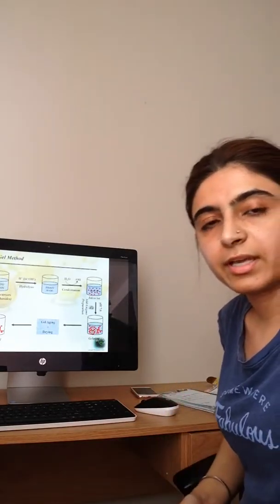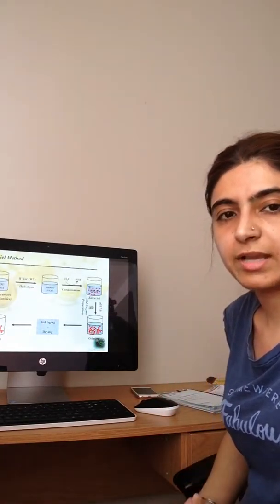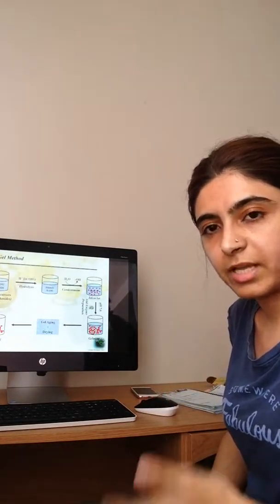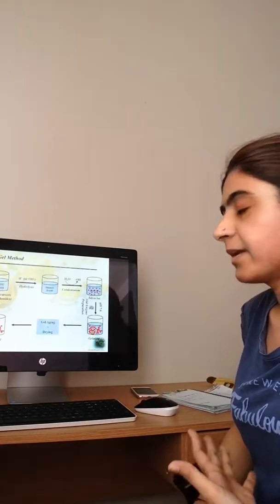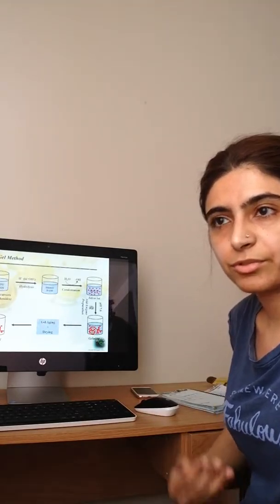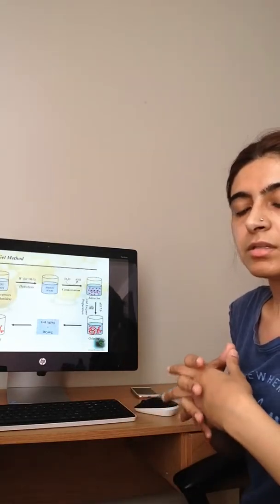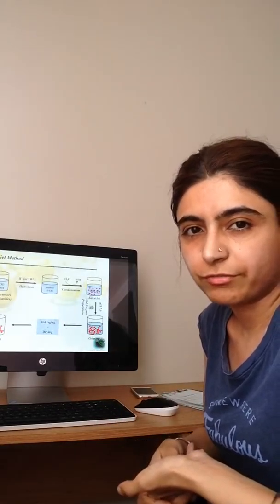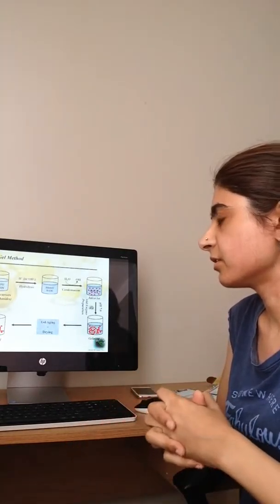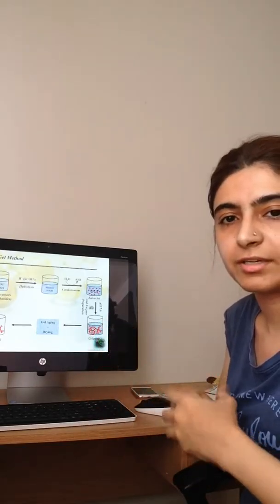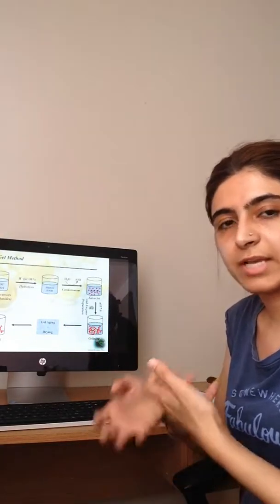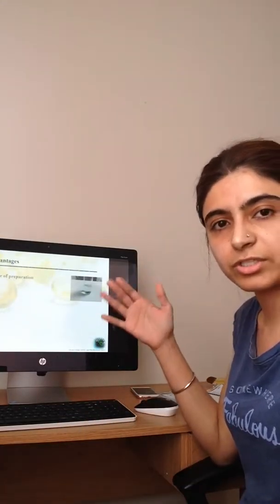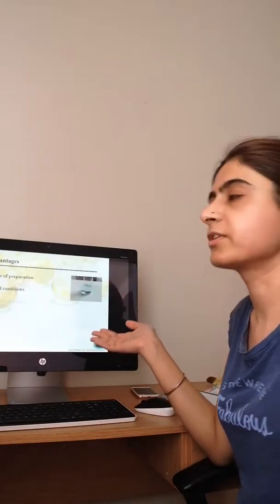Now the enzyme is usually encapsulated in the form of a suspension which is added in a certain buffer of a certain pH to this silica sol, helping it to undergo gelation. The gel is then allowed to age for a certain amount of time to strengthen the silica gel network, and is then subjected to drying, which eventually leads to the formation of a xerogel depending on the method used for drying. And this xerogel then contains the silica gel powder which has the enzyme that is to be encapsulated. Now we can see that water and alcohol are byproducts of this reaction.